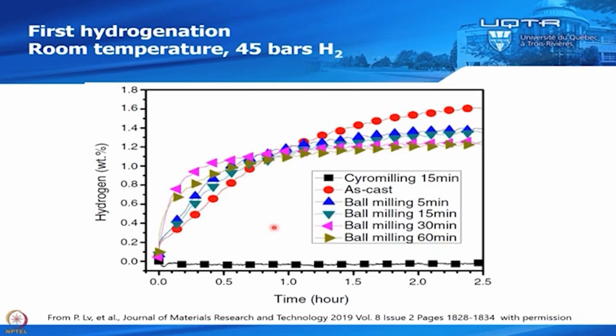It's because we mill in air, and then we have formation of oxide. And as we saw in part 1, in order to hydrogenate, the hydrogen has to go through the oxide layer, and here the oxide was probably too thick and it was impossible. So in the future we will do this experiment again, but under argon, and then we're confident that the sample will then absorb hydrogen.